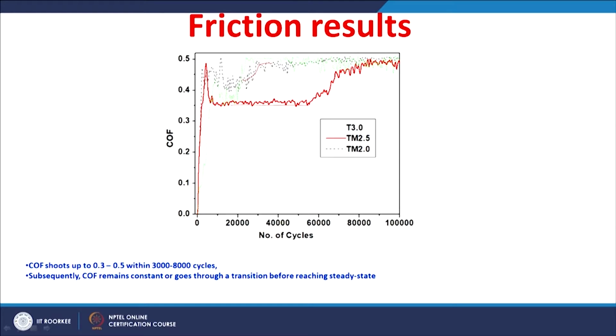You can also see for the 3% yttria stabilized zirconia, immediately after around 20,000 cycles, it goes to a higher coefficient of friction of around 0.5, whereas with the ceramic with 2.5 mole percent yttria, after reaching the peak state in the running-in period, it goes to a lower coefficient of friction of around 0.35, and after around 40 to 50,000 cycles it again shoots up, and beyond 60,000 it goes to the higher coefficient of friction of 0.5.